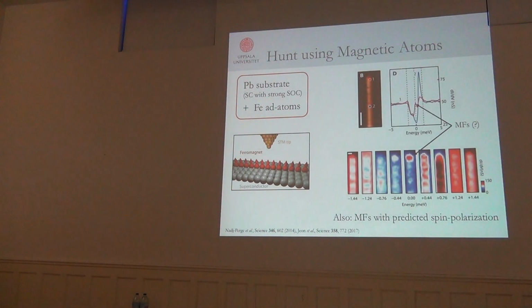So this was the first data coming out of Princeton, scanning through with energy, and at 0 energy there was a state sitting at the end of the wire here, whereas the sample taken in the middle of the wire had nothing particularly happen at 0. There are states sitting there, and those would be what's called Yu-Shiba-Rusinov states, or Shiba states for short, that we heard a little bit about on Monday, I believe. So there are other states around, but it looks like there's something sitting there at 0.